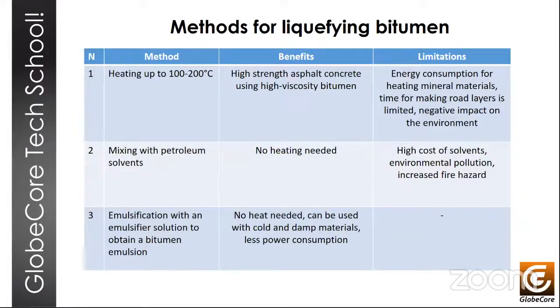There's also a third way: emulsification. Asphalt concrete and other road building mixtures prepared with emulsified bitumen, such as cast emulsion mineral mixtures, slurry seal, microsurfacing, cold asphalt, and asphalt granular concrete, gain strength through the process of the emulsion breaking into its ingredients - bitumen and water.